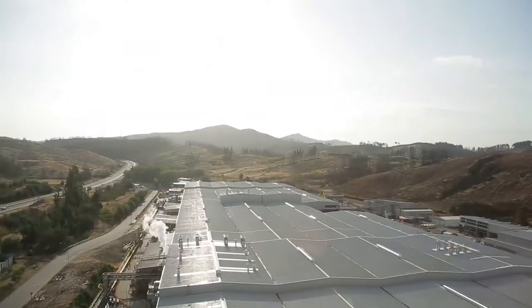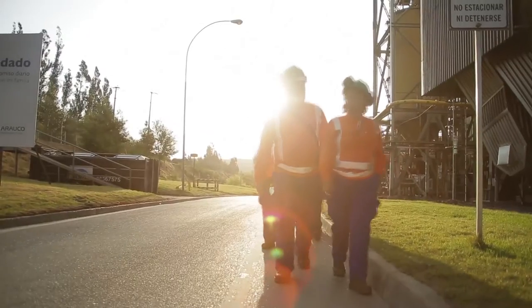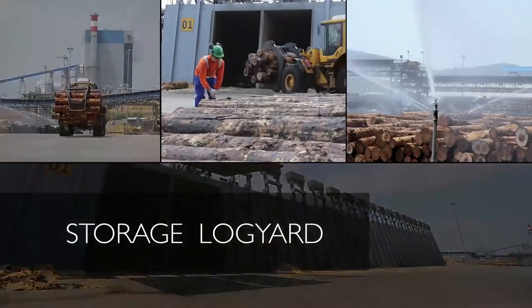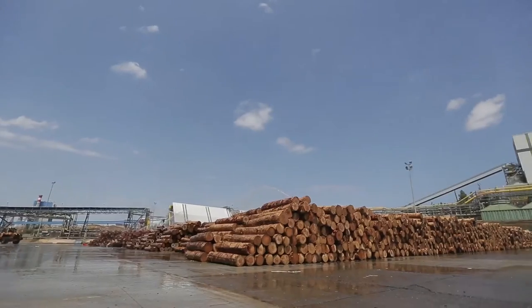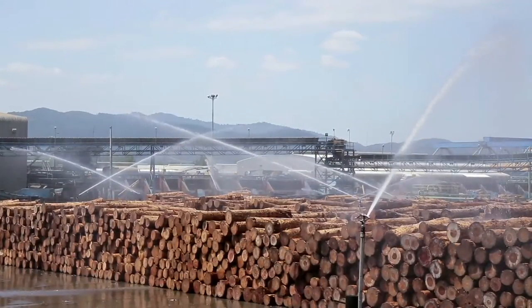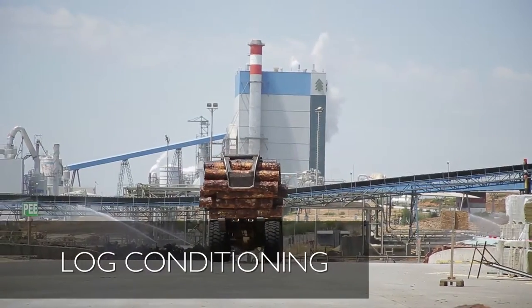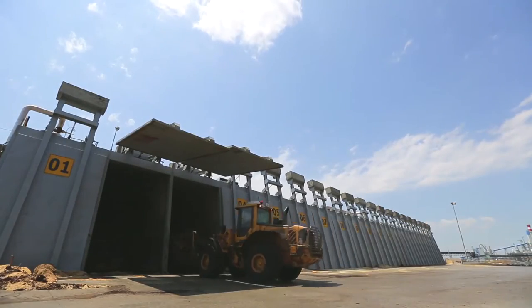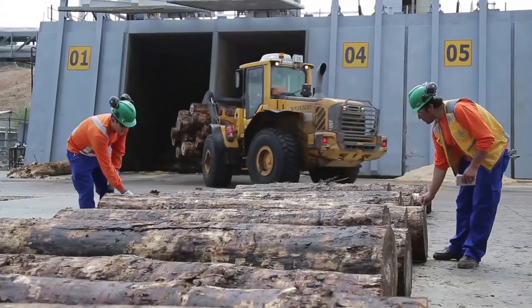We invite you to learn about the production process of both plywood mills — Arauco and Nueva Aldea. The process begins at the log yard, where a continuous watering system keeps the logs, already debarked, under humid conditions to avoid degradation. The logs are then taken to the conditioning chambers, where they are kept under hot water for 18 hours at 85 degrees Celsius to improve the wood's plasticity.